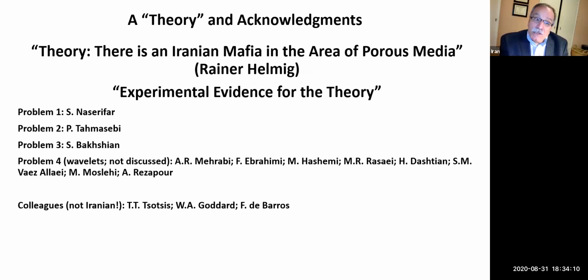Not only that, we also showed, and this was a paper about 23 years ago, that if there is crossover in the data, which means that you are in one regime and then you move to another regime, or you are in one area of the porous medium and you go to another area, and there is a clear transition between the data, wavelet transformation easily detects that. Then we moved on to single phase flow.